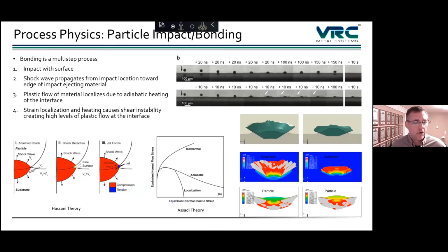This explains this a little bit better. The upper images show a particle impacting on a surface. That particle creates a jet from the interface, and that jet is what cleans the surface and creates that high quality bond. But another part of this is plasticity. So the first jet that forms is really from a shock wave. The second jet that forms is from the plasticity of the material itself. So that's down at the bottom right. And both of these are needed in order to get a high quality bond. The shock wave jet cleans the surface, and then you get this high amount of plasticity between the two particles, and that is what gives you your good bond.